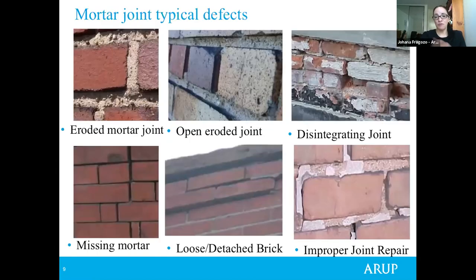Mortar joints. Some of the typical defects on the mortar joints are eroded mortar, which could be due to erosion from wind or disaggregating of the lime component of the binder. With open eroded mortar joints, that is the loss of the outer layers of the mortar, we should be looking at the depth of the erosion of the grout in relation to the outer surface of the brick, and the condition of the brick surface and edges. If possible, we should try to find a reference point, maybe an area where the original tool grout still maintains its original condition, so we have a point of reference on the location and the extent of that deterioration on the mortar joint.